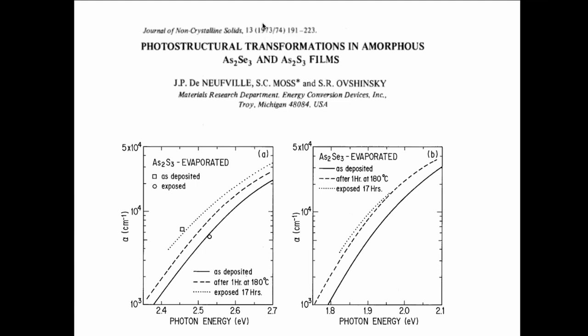The photodarkening effect was first observed in the early 1970s. When arsenic sulfide is illuminated with light, the absorption edge shifts to lower energy — this is photodarkening. If the material is annealed close to the glass transition temperature, the initial properties are recovered. In subsequent cycles, transmission can be cycled reversibly between the illuminated and annealed states — it is a photostructural change.